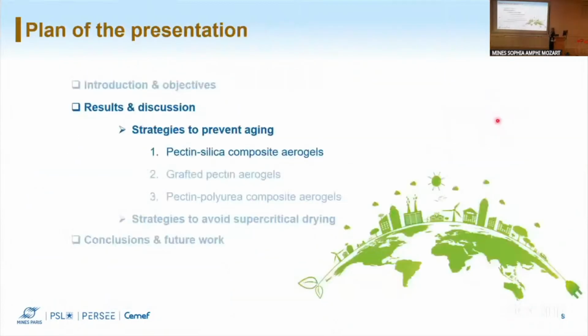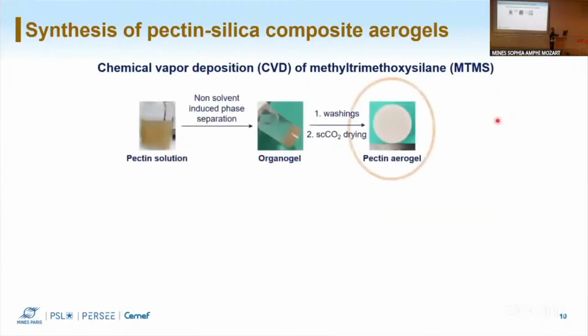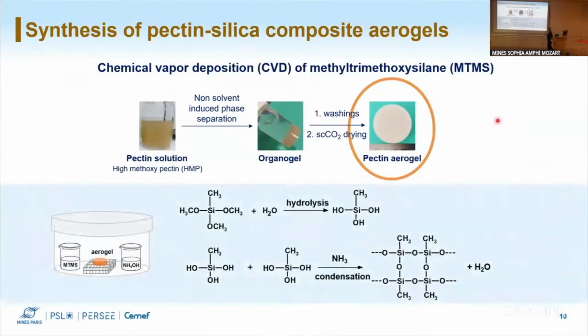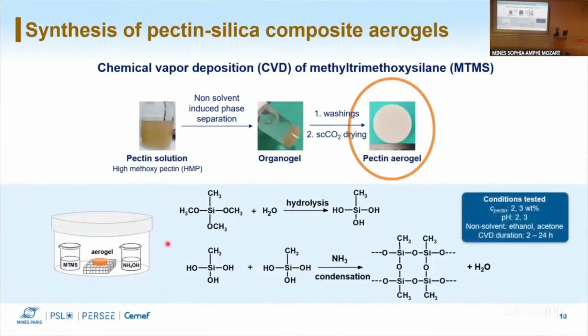Let's start seeing some of the results. Starting with the pectin silica composite aerogels, we did chemical vapor deposition of methyltrimethoxysilane on our final aerogel. So we worked on the dry material, and for this work we used high methoxyl pectin. We can see here the aerogels were placed in a closed container with the reactant and the catalyst, and they were left so that the silica phase can be developed. We varied different parameters such as the initial concentration and pH of the pectin solution, the non-solvent used for coagulation, and the duration of chemical vapor deposition.